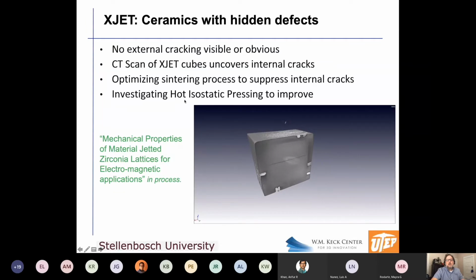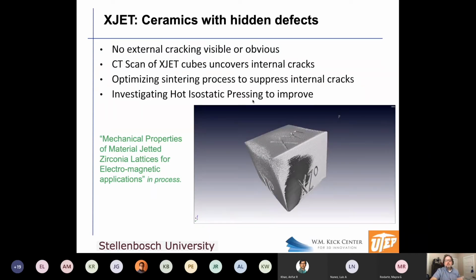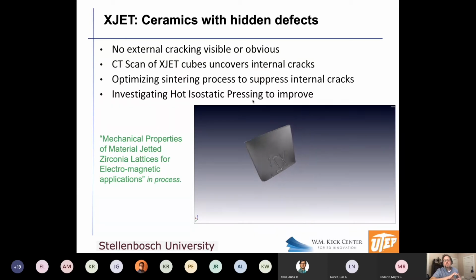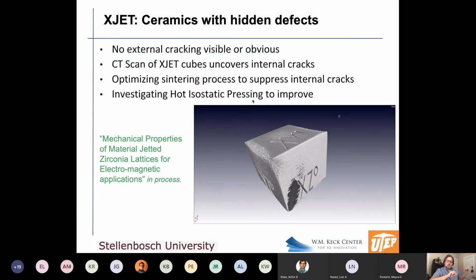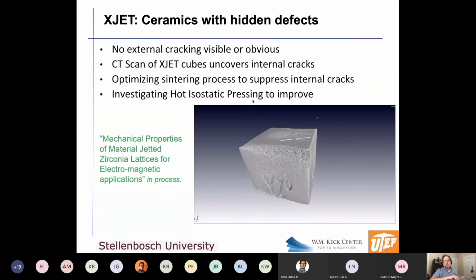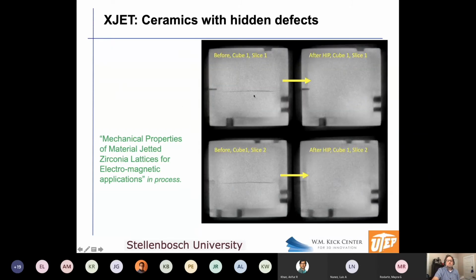But there's something called hot isostatic pressing, where you can put these into basically a hot liquid oil, and it gets compressed at really high pressure, really high temperature. And they do this often for titanium parts that go into airplanes to close off internal pores. Any pore or crack that goes to the outside, the oil would get into that and it wouldn't help. But any internal crack, it can potentially fix. And so we're about to publish a paper where this is that same cube. This is 2 different CT slices before and 2 different CT slices after. And you can see that that crack is gone.